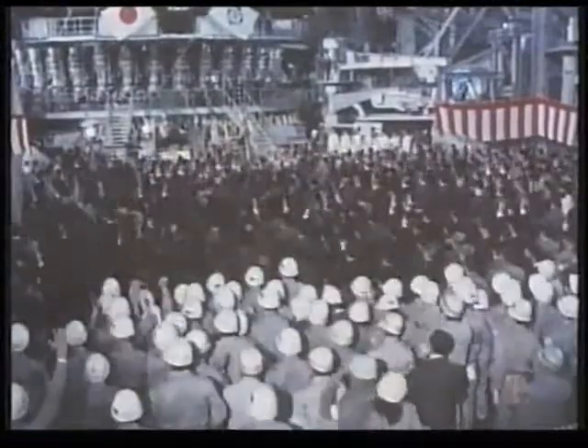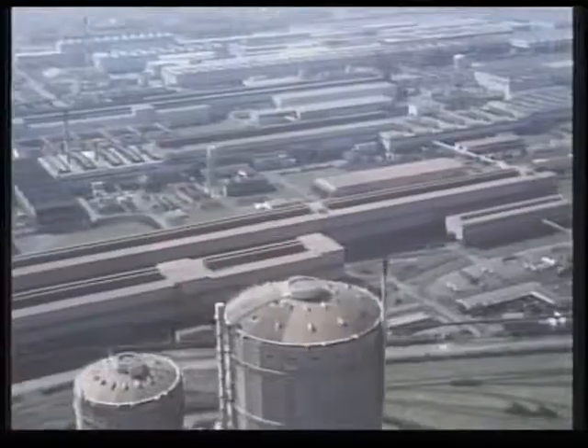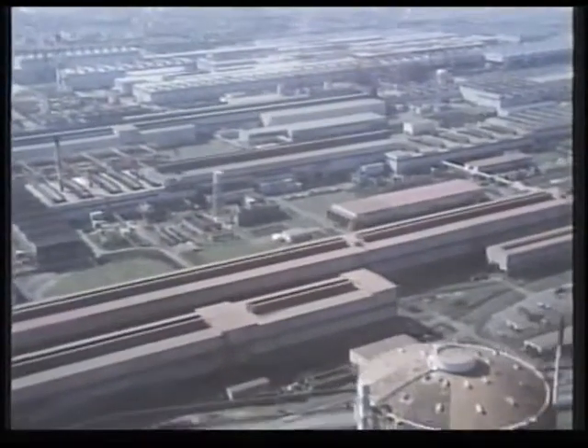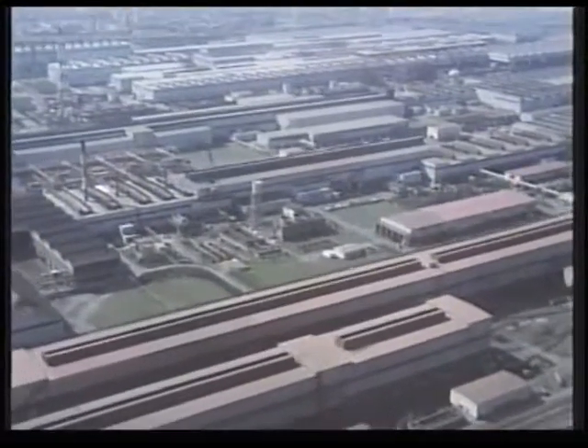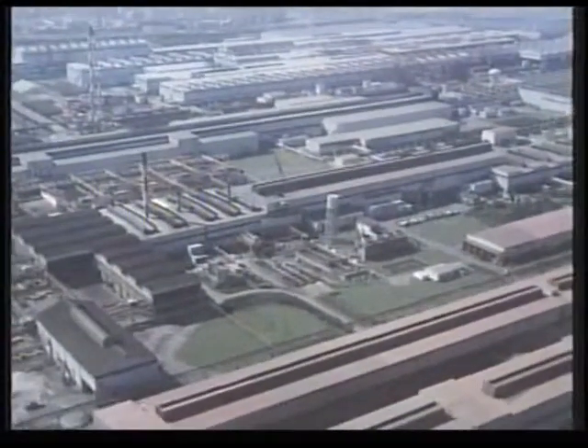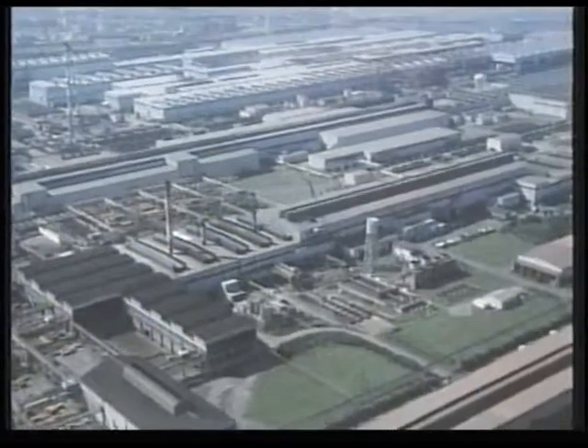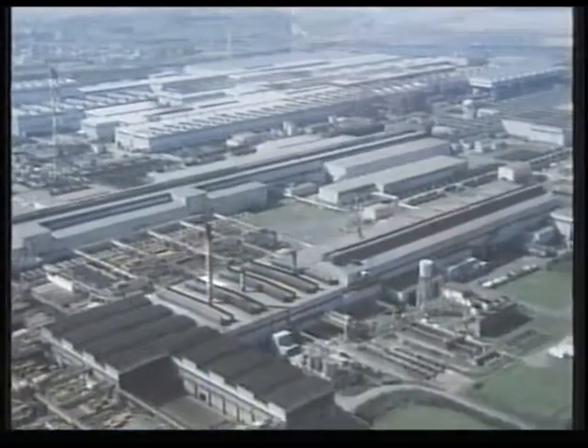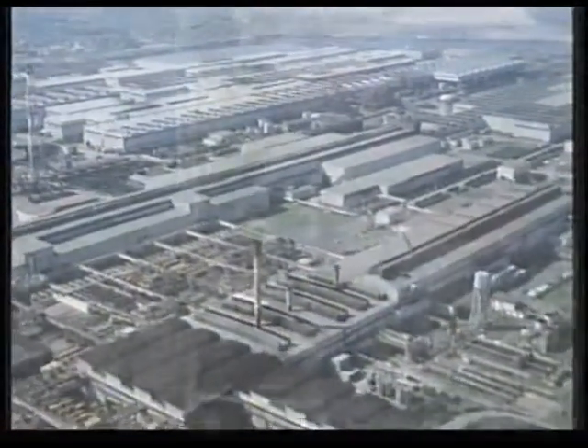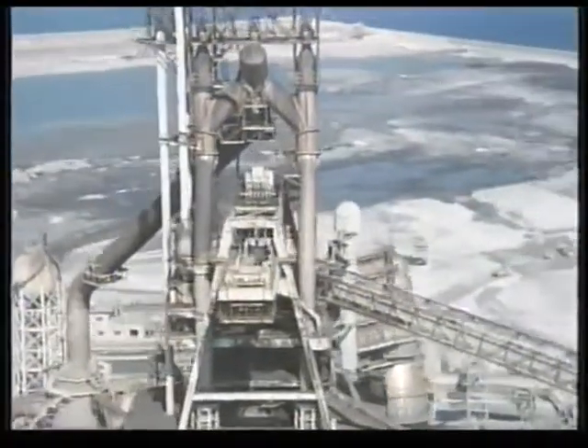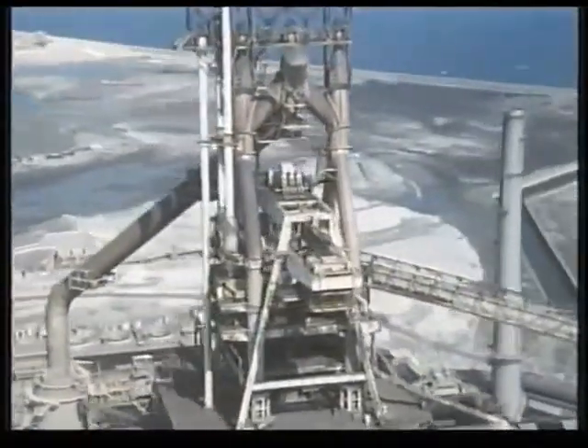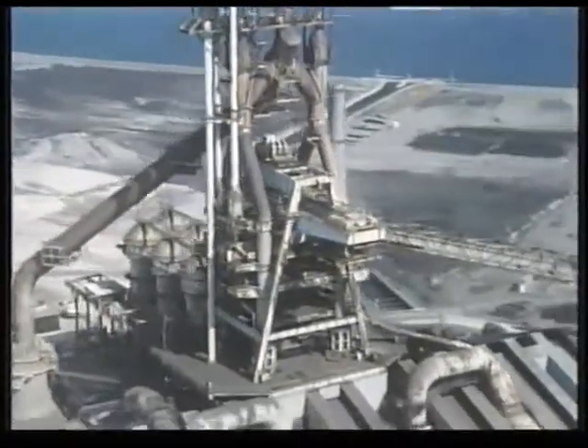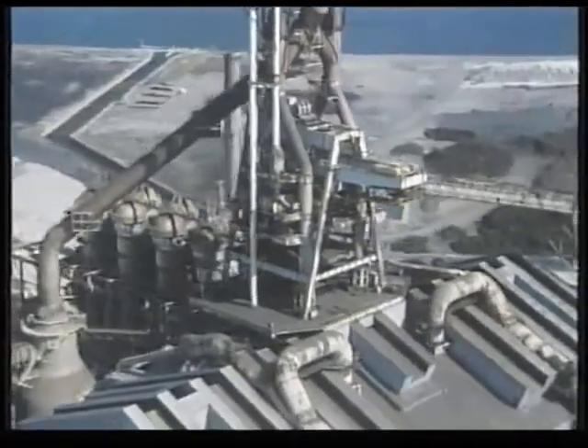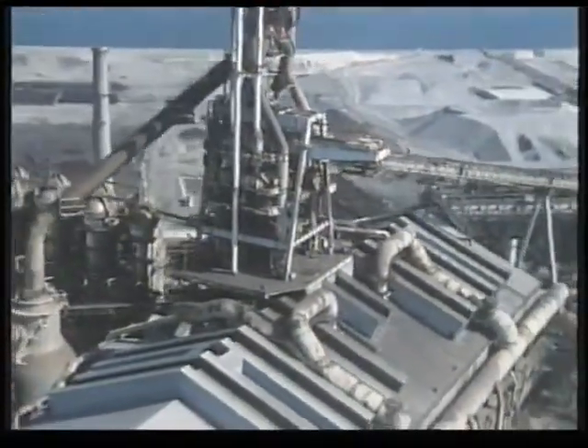By opening entirely new steelworks, the Japanese had increased their output 10 times over since the war. I think the thing which impressed me most was the scale on which modern steelmaking has to be operated to be successful. The Japanese had blast furnaces which didn't make any less than 10,000 tons a day. Now, in our case, the largest blast furnace we have made only 2,750 tons per day.